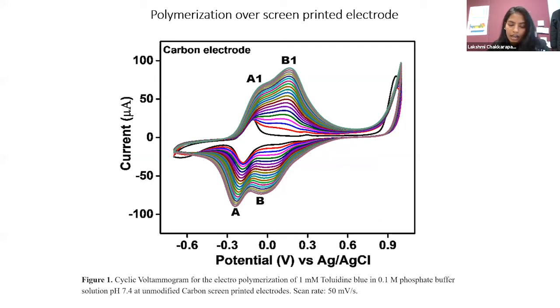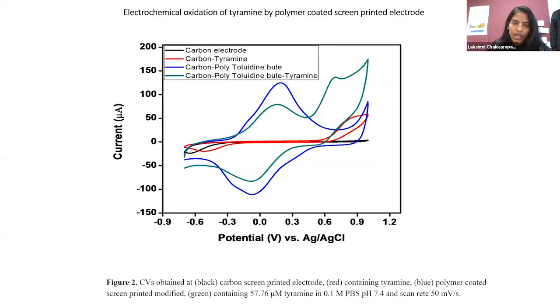And finally, after we get the polymer electrode, we just take it out from the instrument and then wash it with distilled water, in order to remove the monomer particles from the electrode surface. And then we use this polymer electrode to analyze tyramine.